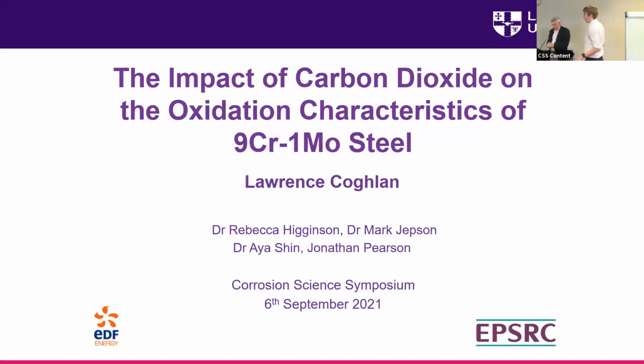I think there are a lot of different ones, and personally I think there are several triggers that can lead to it. I think that's one of them. But some of the other ones, for example carbon saturation, are similarly linked to the chromium being used up because it's all tied up in carbides. Some of the other theories for why it breaks away are because effectively a carbide wall forms at the surface by the oxide, so the material is no longer able to act as the carbon sink, and that triggers breakaway. And then there's also geometry, especially with the fin samples. As the oxide continues to grow, you've got it growing around the fin, so that's what leads to cracks. But yeah, there's a lot of discussion at EDF about what breakaway is to start with, so that's one of them. Okay, thank you very much.